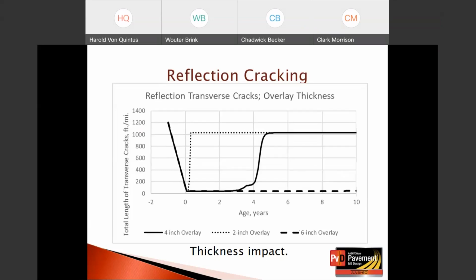This next graph now shows, again, the impact of asphalt overlay thickness, but for transverse cracks. And we see basically the same thing. We have the transverse cracks for a 4-inch overlay, 2-inch overlay, and a 6-inch overlay. The 2-inch overlay is the short dashed line, and you can see they occur very quickly, and once they start to occur, they propagate very rapidly.